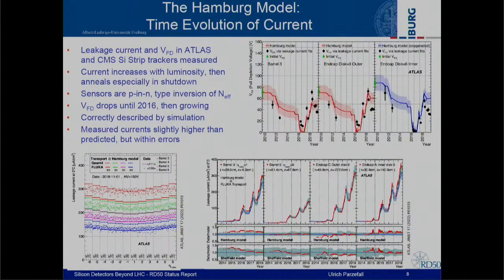Starting with this top plot, I should point out this is all traditional p-in-n type silicon, so you have a type inversion of the doping concentration going on. This Atlas plot shows, for one of our barrels and for two end cap disks or selections of end cap disk modules, how the full depletion voltage changes as a function of time, meaning radiation. The black points are the measurements, and by and large the change of the full depletion voltage is very well described by the Hamburg model.